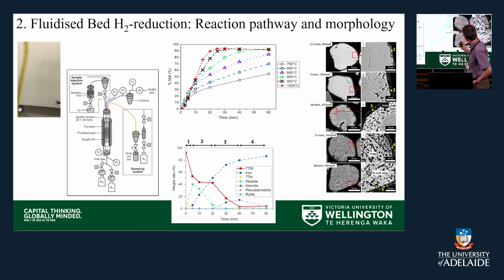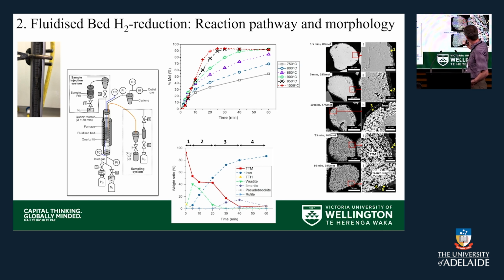And when we do that, what we see is that we can react it at very high temperatures, because as it reduces, it forms a titanium-rich skin around the outside. And so this is a situation where our contaminants are actually helping us. They're making it easier for us to run this reaction because they're coating the outside of the particles and they're preventing us forming wet liquid metal on the surface of the particles, which would otherwise make it stick.